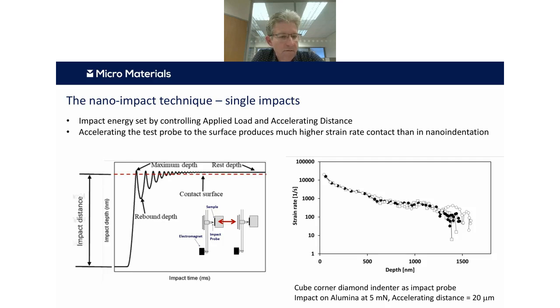So all of the subsequent bounces are elastic typically, so all of the damage is done during that first bounce. And you can see on the right there is an illustration with a cube corner probe hitting a bulk alumina sample. You generate these very, very high strain rates compared to a normal quasi-static nano-indentation test where the strain rate might be something like 0.1 per second. So we're many, many orders of magnitude higher than that. So that gives us more relevant information for these high strain rate contacts that happen in the real world.